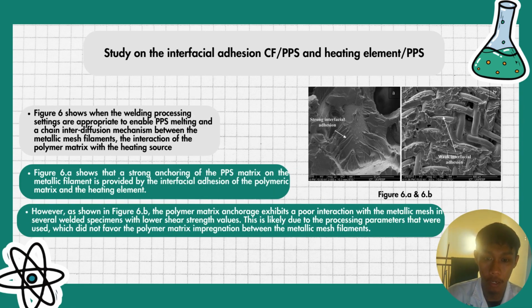Figure 6 shows that when the welding processing settings are appropriate to enable PPS melting and a chain interdiffusion mechanism between the metallic mesh filament, there is interaction of the polymer with the heating source. Figure 6a shows that a strong anchoring of PPS on the metallic filament is provided by interfacial adhesion of the polymeric matrix and the heating element. However, as shown in figure 6b, the polymer matrix exhibits a poor interaction with the metallic mesh in several specimens with lower shear strength values.